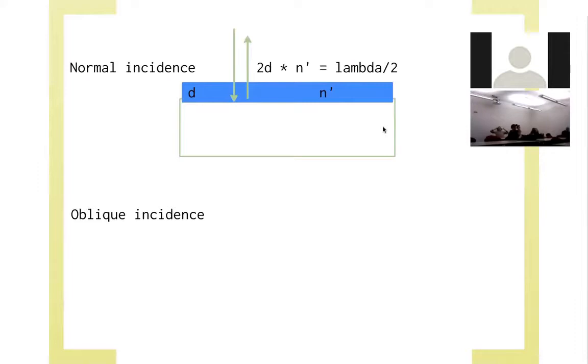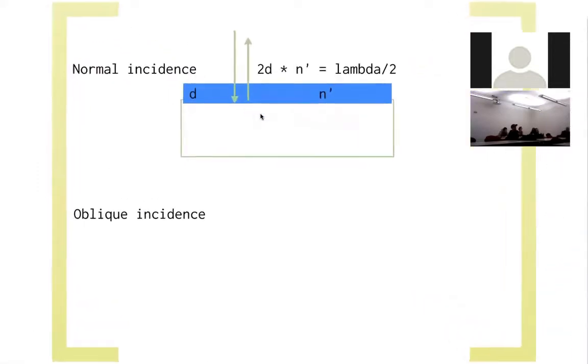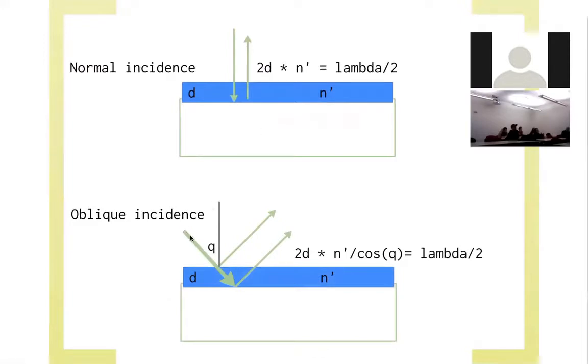Okay. Now for oblique incidence, of course, the problem is very similar. You just have to come in at an angle. The way you solve it looks like that, right? So light comes in, there is a reflection from the top interface, there's another reflection from the bottom interface, and let's say theta is this angle here, and then you want to make sure that this ray interferes destructively with this ray, right? So the way you do it is you compute the path length, which is, from this point, you go down and up, and figure out what that distance is. And with this very simple geometry, it just turns out to be D over cos theta plus D over cos theta. So you get 2D over cos theta times n prime equals lambda over 2. And then you can figure out D. So theta is 45 degrees. You can plug in the numbers and you get the answer.